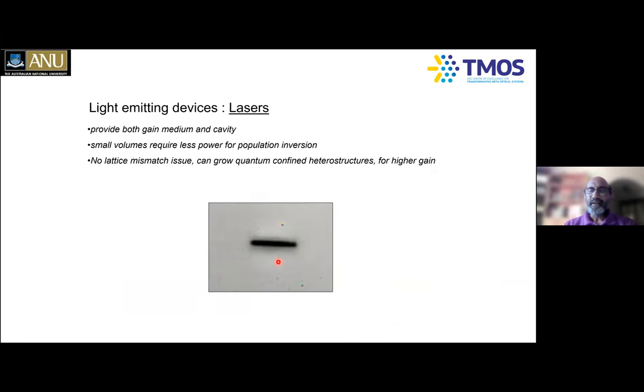If you take a nanowire of the right dimensions and right diameter, and you excite this nanowire with a laser pulse, light starts propagating along the length of the nanowire, because the nanowire starts behaving like a waveguide, because of the high refractive index of this nanowire of 3.4, while the surrounding air or vacuum refractive index is 1, for example. And also, both ends of the nanowire act like mirrors because of the refractive index difference again. Because we're using these III-V semiconductors, they are direct band gap semiconductors, they've got gain, and then you also get a laser cavity without having to put mirrors or anything of that sort. So that really opens up opportunities for us: if we design these nanowires correctly and grow excellent quality nanowires, each nanowire in principle should act like a laser.